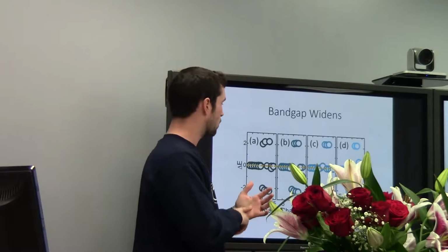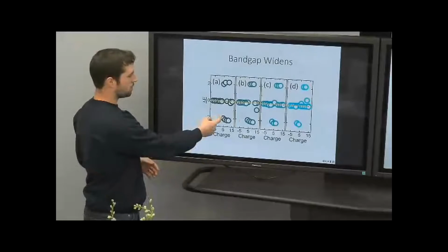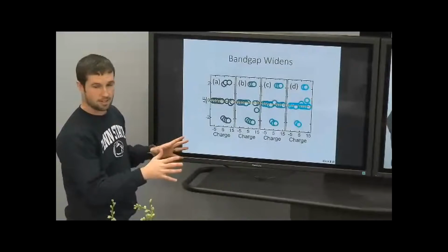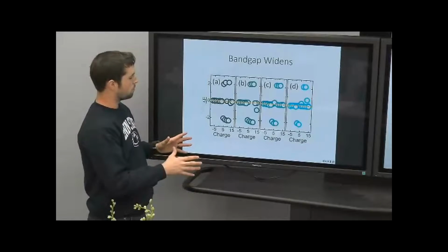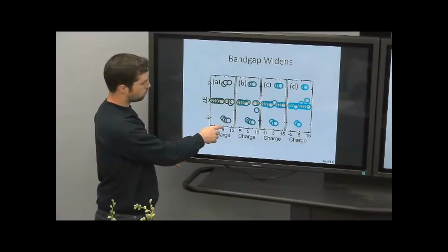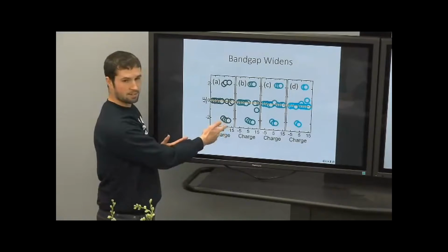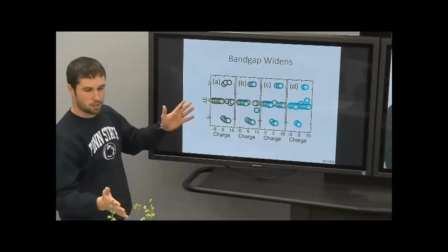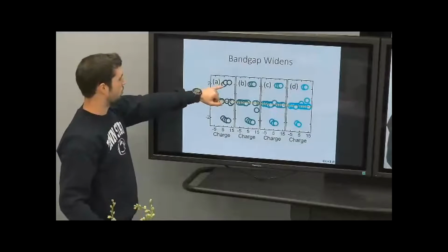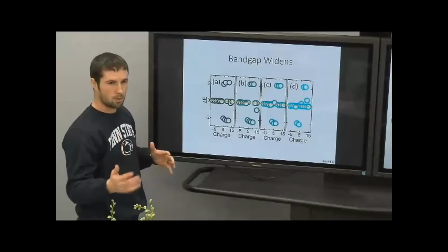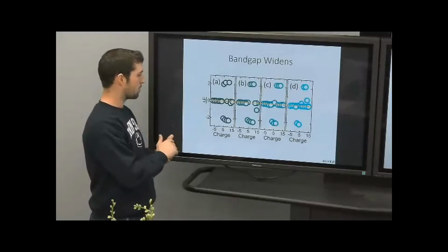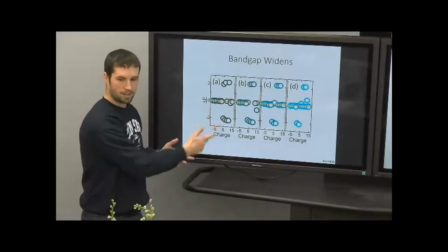I didn't mention we looked at different spins of 0, 1, 2, and 3. So this is spin 0, 1, 2, and 3. And then we looked at the band gap for all these different oxidation states. And for high oxidation states from about 3 to 10 in these models, we can see that the band gap considerably widens to about 2 eV. And since we did this for both alpha and beta electrons, we multiplied the band gap of the beta electrons by -1, so that's why we have a negative band gap here.